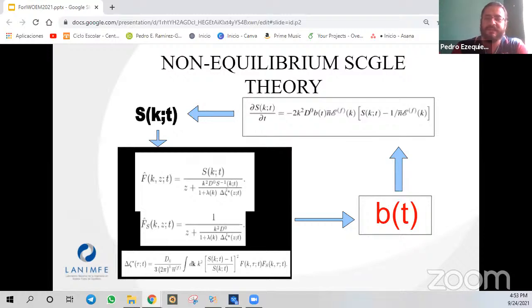This theory contains two levels of description, one macroscopic for the local density average and the one-time correlation function, which is something like a time-dependent radial distribution function or structure factor if we go to the Fourier space. The other level is microscopic in the sense that it describes the relaxation of the local fluctuations of the liquid through a waiting time-dependent intermediate scattering function. The two levels are connected by the time-dependent mobility, B of t, which is obtained from the microscopic level and governs the macroscopic one.